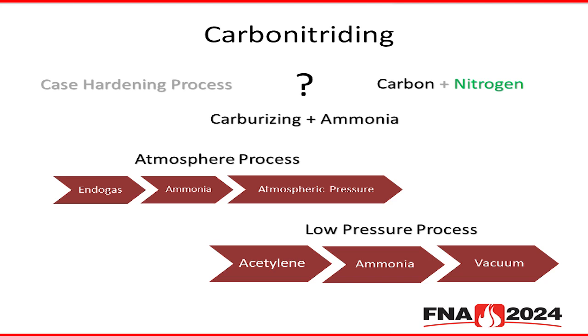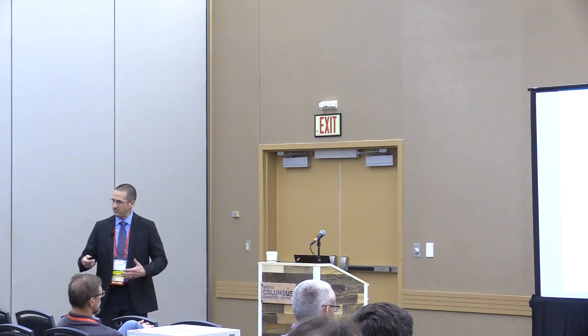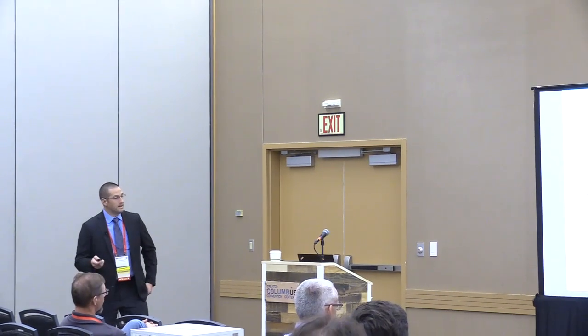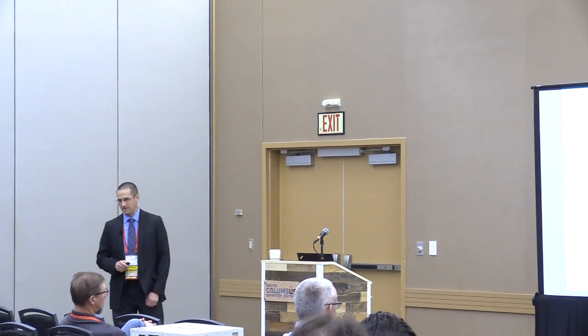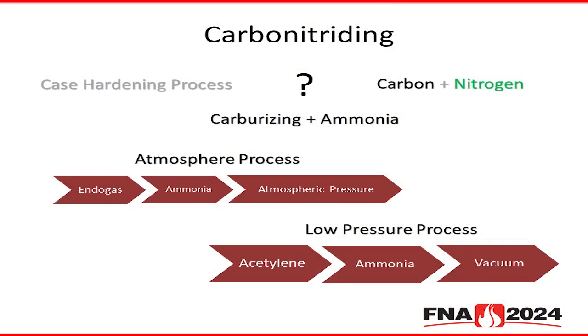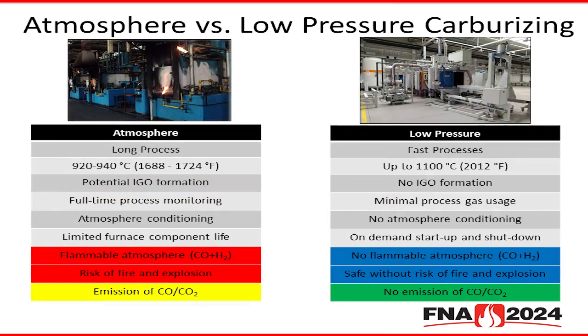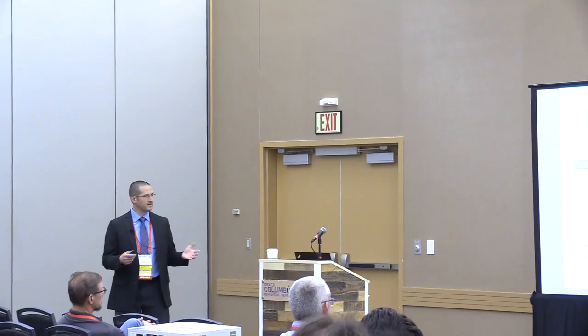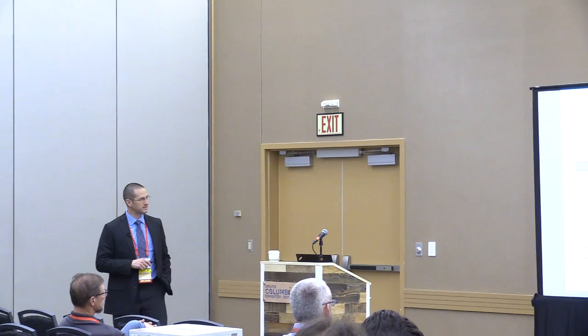In the normal atmospheric process, we would employ endogas as the carbon source, ammonia as the nitrogen source, and this would all be done at atmospheric pressure. On the other hand, low-pressure carbonitriding uses acetylene as the carbon source, ammonia, again, as the nitrogen source, but this time we do it in a vacuum. Looking at a few more differences between the two processes, atmosphere typically tends to be a rather long process, typically run between upper 1600 to lower 1700 degrees Fahrenheit.